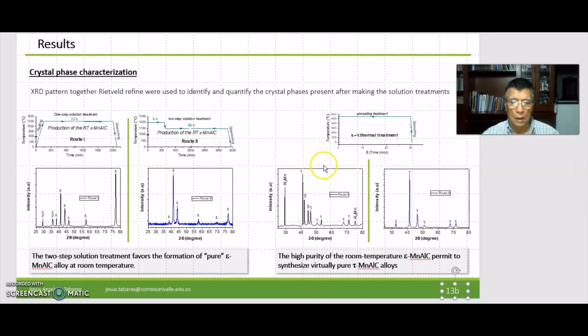Here I present X-ray diffraction results for the alloys after making the annealing treatment to induce the epsilon to tau transformation. The epsilon phase-based alloy obtained by following route 1 produces a solid heterogeneous mixture alloy where the majority phase, around 90%, is the expected tau manganese aluminum. This is the tau manganese aluminum. And the presence in this case of aluminum 6 manganese and beta manganese phases.